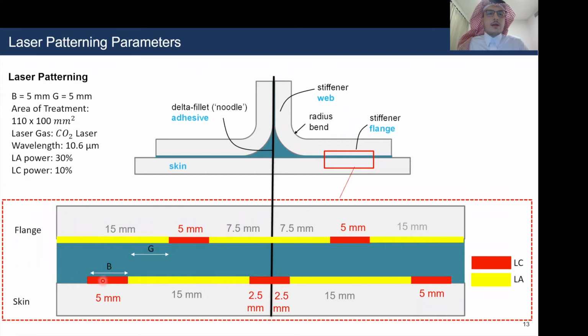And the area which was treated was 110 by 100 millimeters squared. And the gas used was carbon dioxide, which had a wavelength of 10.6 micrometers. The LA power was 30%, and the LC power was 10%.